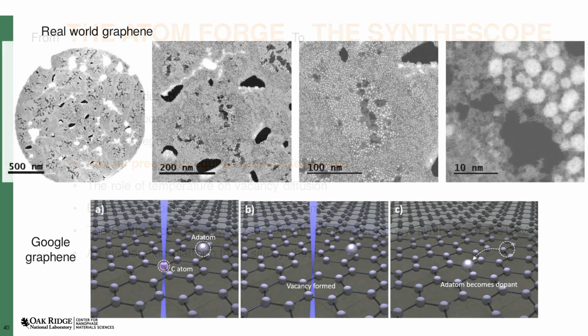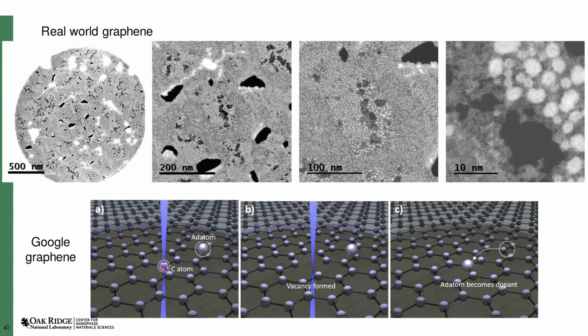To move this in the direction of being a useful tool for fabrication, we need to address several problems lurking in the background. When you Google graphene, what you will typically see is rendered images of a perfect hexagonal lattice like this, or you will see carefully cropped images with a handful of atoms. However, in the real world, graphene looks more like this. The majority of what you're seeing is not the graphene, but the surface contamination. If you have a nice clean sample and you zoom in, you can find these small dark areas where we have atomically clean graphene with nothing on the surface.